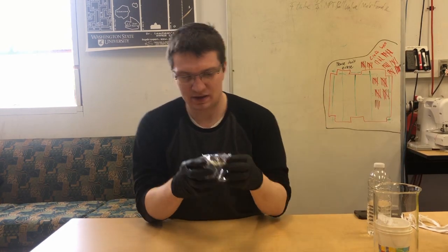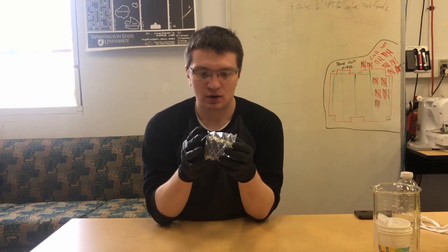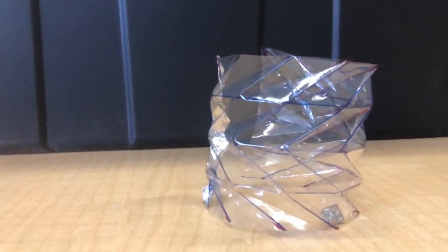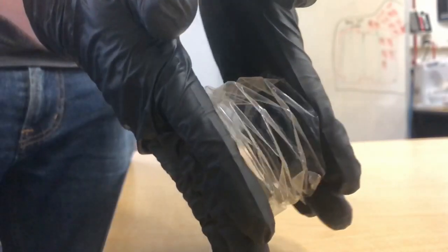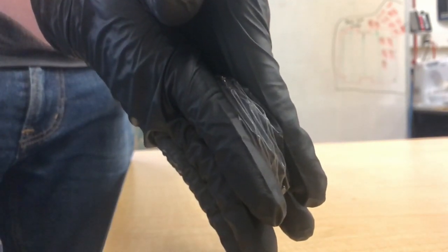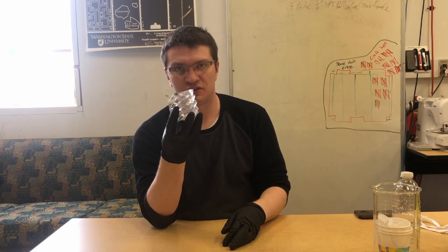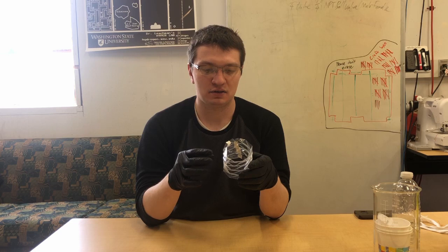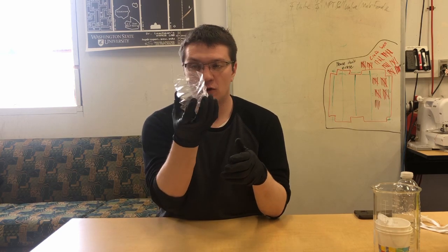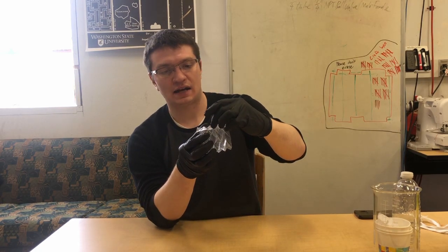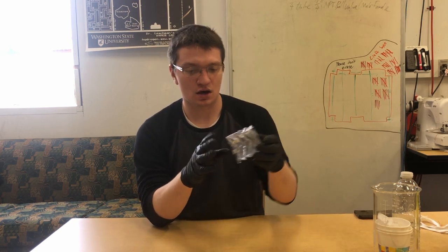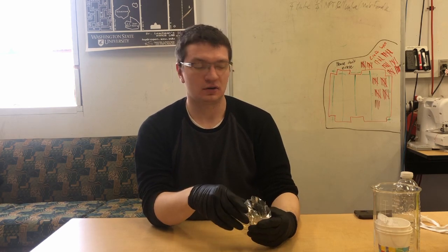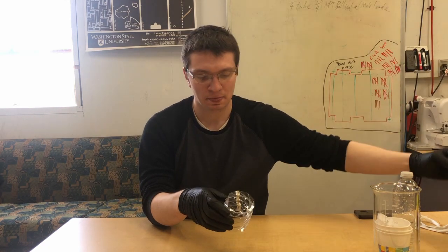So the method that I thought about was, let's try to form your bladder into an origami bellows. You can fold or fabricate your bellows at room temperature. In the case of folding, you can get around all these high stress concentrations because you're folding it at room temperature where there's a ton of ductility in a polymer. And then when you form it as such, the creases here actually act a lot like elastic hinges. And as such, when you compress the bellows, it's primarily just going through elastic deformation, a lot less high stresses than you would see when crumpling a bag.